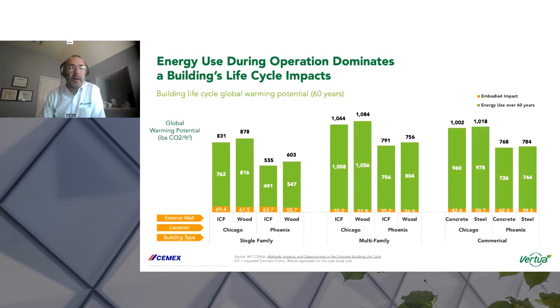This is from the Massachusetts Institute of Technology, their Concrete Sustainability Hub. They looked at different types of building construction throughout different locations, building types, single family, multifamily, commercial, and different types of construction materials, and compared the global warming potential over 60 years. And what we typically see is concrete's almost always going to be higher in that initial, embodied phase, in the embodied CO2 of the materials. But over their lifetimes, they have much lower emissions. And that's because, again, of those inherent properties.